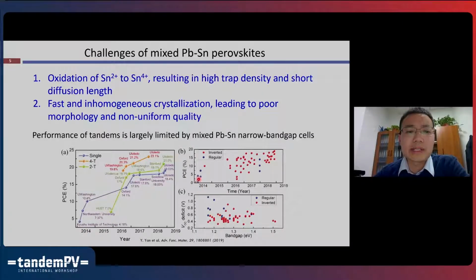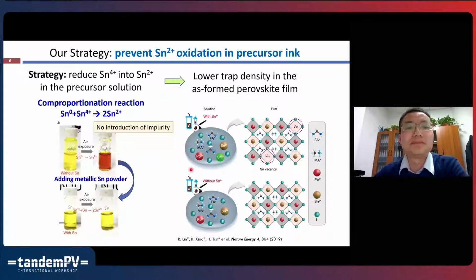In the beginning, when I started my group, we found that the oxidation of the tin 2+ ions directly in the solution is a big problem for making high efficiency devices. For example, if we have oxidized ions already in the precursor solutions, then unavoidably we will get a very high tin vacancy density in the material, and this usually results in very poor materials. Later we found that we can actually solve this problem using a strategy we call the comproportionation reaction.